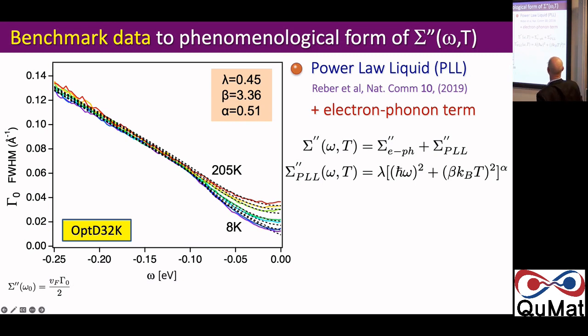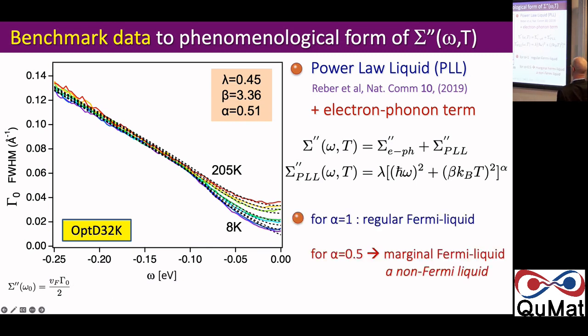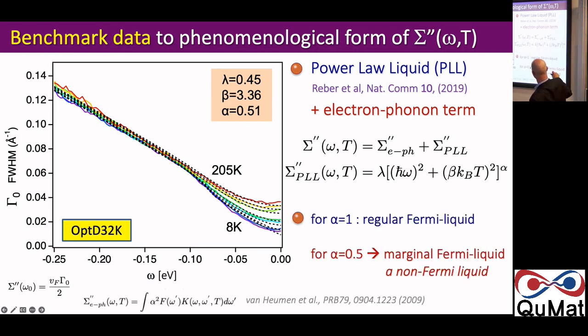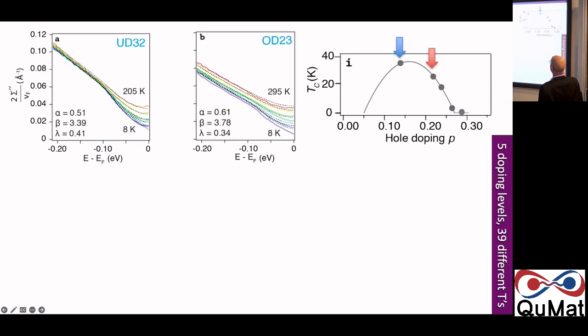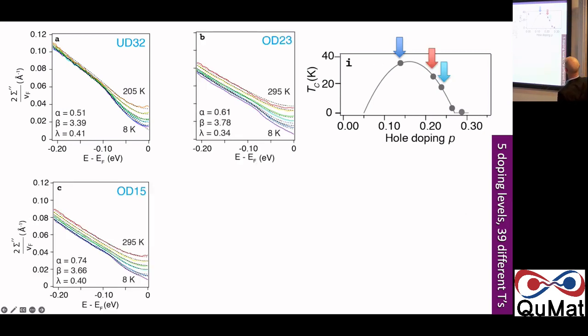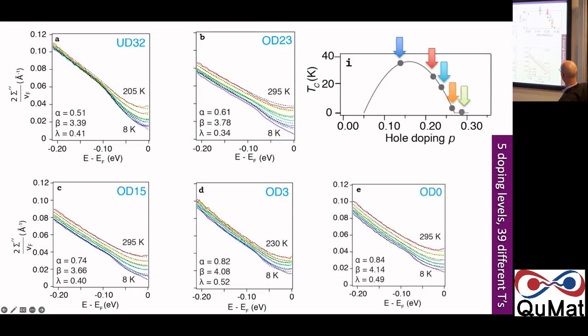Okay. Now there is a phonon in here. You can see this kink in the self-energy, so we've added in an electron-phonon coupling term just so we can properly do a fit, which determines these parameters here. Okay, so these dashed lines are a fit with this power law liquid plus a phonon. It works really, really well. So we do that for 32 Kelvin. So now I'm moving through the doping phase diagram. We're slowly reducing our TC.